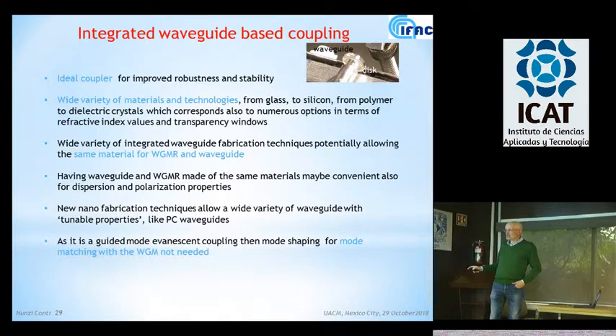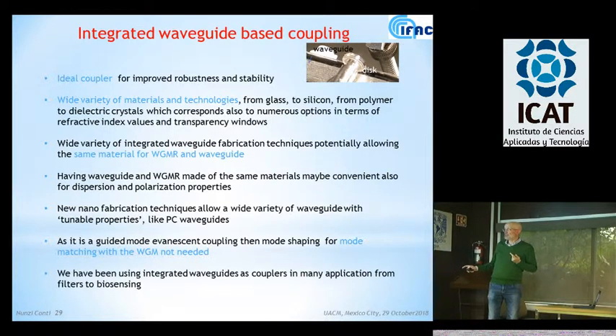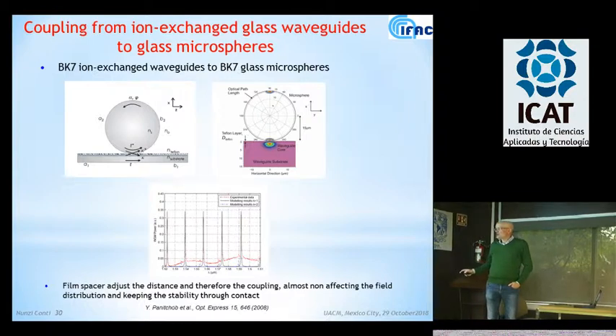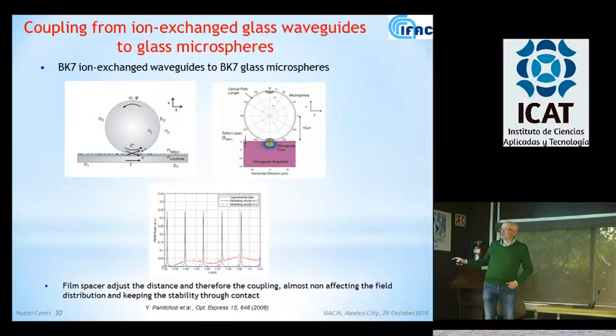And so what we did basically in our case, this is the other important thing, is that mode matching with the whispering gallery mode is not needed. So with integrated waveguide couplers, there was a first experiment we did a long time ago with the group of Professor Wilkinson at the ORC in Southampton, to couple light to a BK7 glass sphere from an ion exchange waveguide, which was the technique we were using, made in the same BK7 glass. And we could excite the modes. We were using a low index Teflon, a low index material, to control the gap and ensure stability, in order to control somehow the separation between the waveguide and the whispering gallery mode.